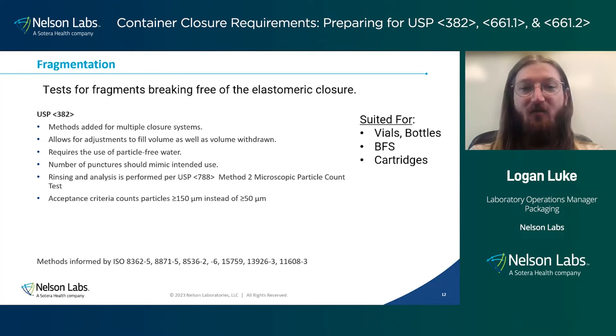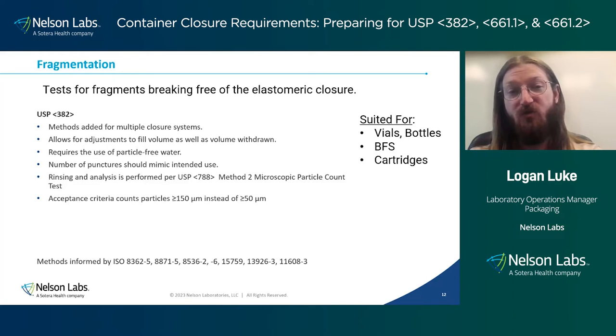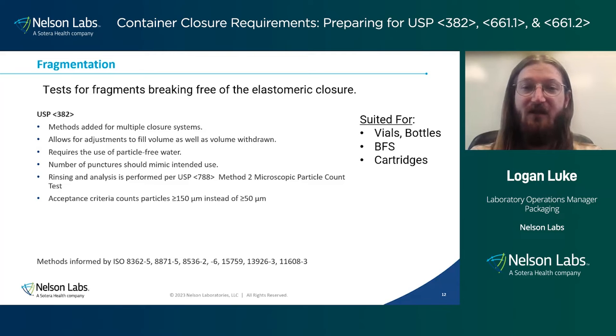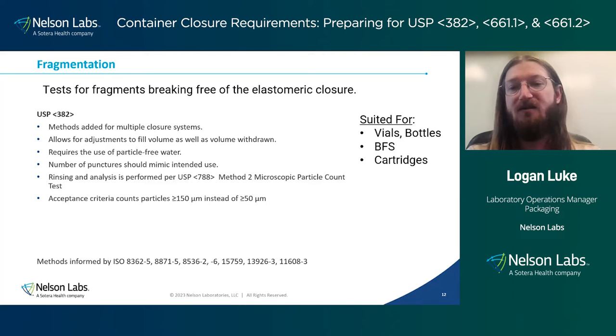And since there are now multiple closures that can be tested, your fill volume, as well as the volume that you're withdrawing, is adjustable as well. What is big here is that there's now the requirement to use particle-free water, which was not a requirement before. The number of punctures that you're using needs to mimic your intended use rather than just having a prescribed number. And your rinsing and analysis is performed according to the particulate method, USP 788. Just a quick note too, that 150 microns is measured based on the longest linear dimension.